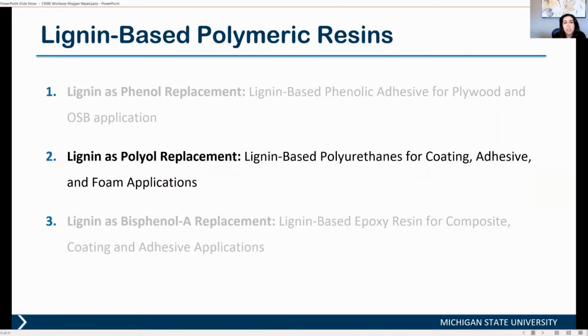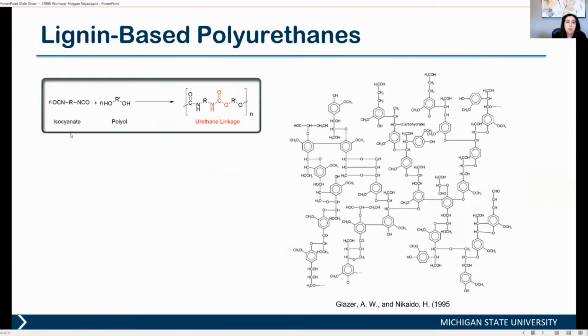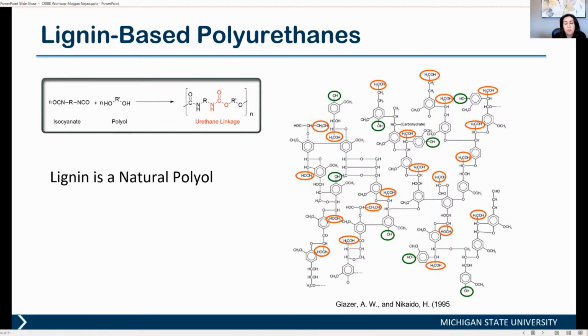The other project is that we can use lignin to replace polyol in polyurethane applications that could be used for coatings, adhesives, or foams. When we're talking about polyurethanes, there are two major components: diisocyanate and polyol. They react together to form the urethane linkages. If you look at the structure of lignin, it has many aliphatic hydroxyl groups and many aromatic hydroxyl groups. Basically, lignin is a natural polyol. It's a very complex structure, but it has these hydroxyl groups as a natural polyol that we could use for different polyurethane applications.